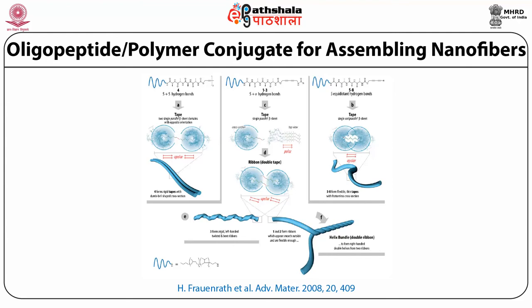AFM images show that compounds one, two, and three form very long fibers with high aspect ratio; these fibers have parallel beta sheet domains with very pronounced twisting. For compound four, no twist was observed — only flat tapes from a single parallel beta sheet unit. These molecules fall into three classes: compound four, where both sides of diacetylene are flanked by polyisoprene and oligopeptide, forms tape-like structures through parallel beta sheet with opposite orientation; compounds one to three form ribbons by helical tapes twisting around each other; and the third class forms single antiparallel beta sheet tapes with flexible, featureless cross sections.